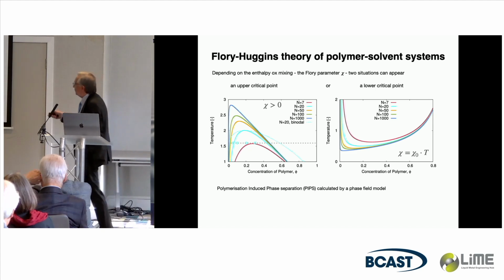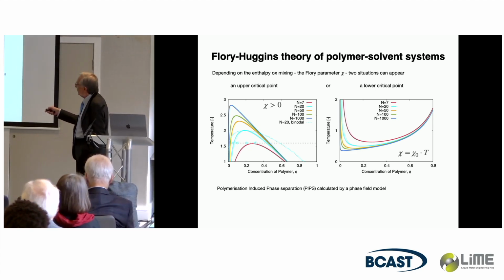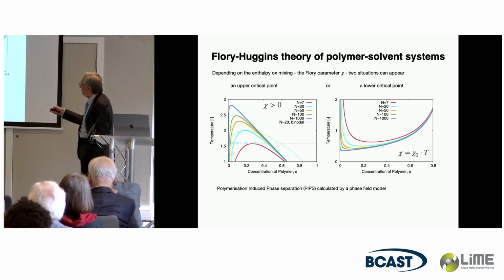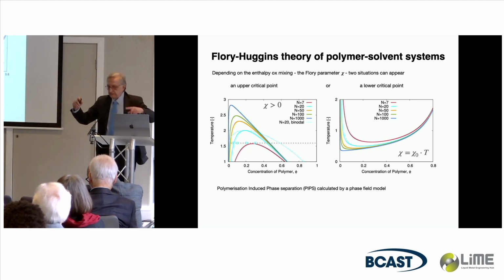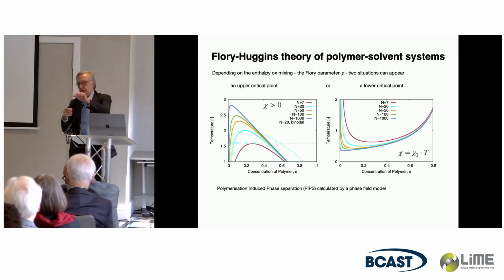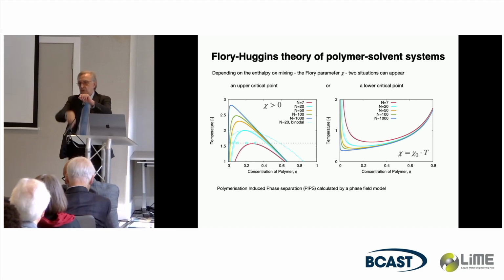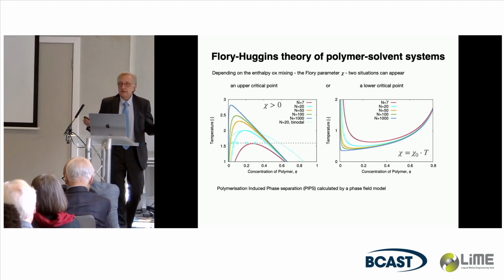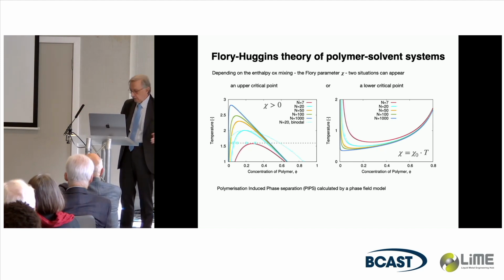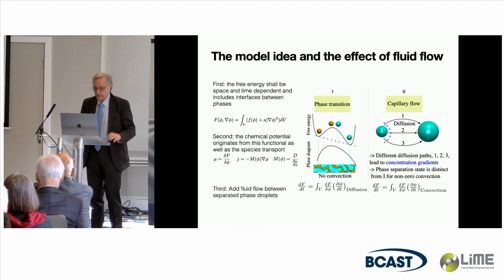So, the point here is what you can see here. If you initially have a concentration here, initially everything is miscible. As the degree of polymerization goes from 7 to 1000, the points move into the spinodal. Here we only plotted the spinodal, that's a binodal here. So, since it's time dependent, a state point runs from a single phase field into a two-phase field. And then everything should happen that we know from immiscible alloys.